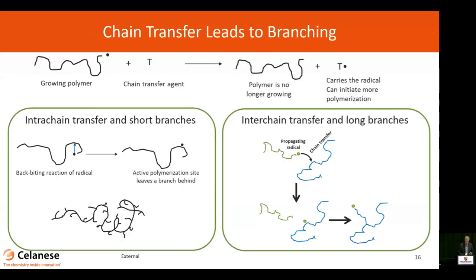So thus far we've created a fairly simple picture of what this material is like and how it's characterized. Now we have to jump to the part of EVA that makes it more complex. If you recall, I put up a slide earlier of all the different mechanisms that you can encounter in free radical polymerization. One of those is chain transfer. One of the complexities of ethylene vinyl acetate copolymers, and in fact all ethylene copolymers in free radical polymerization, is that there is substantial chain transfer to the polymer itself in the reaction medium.